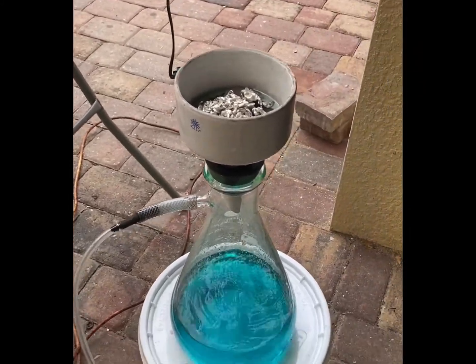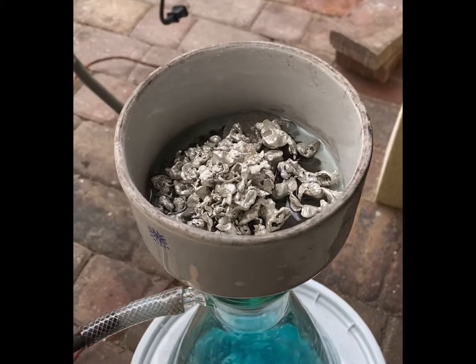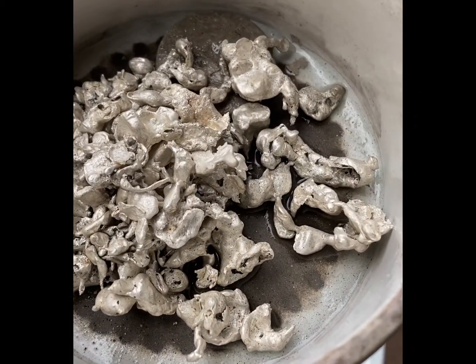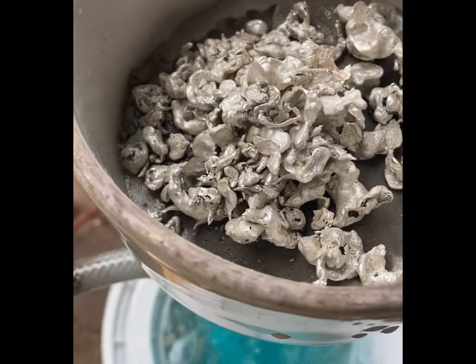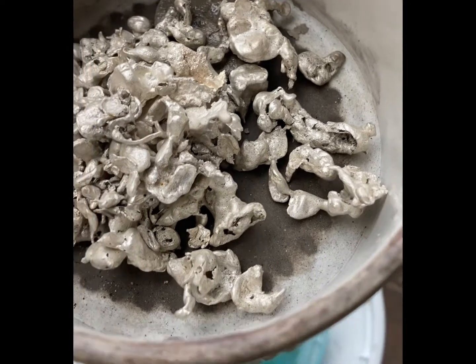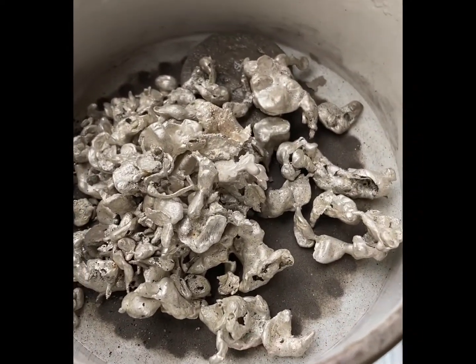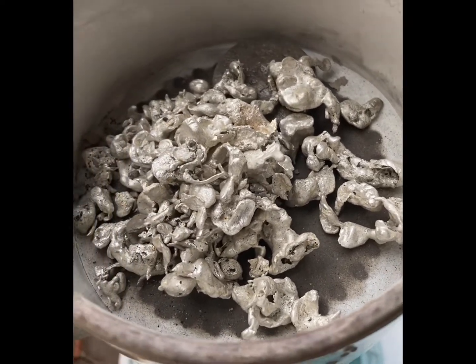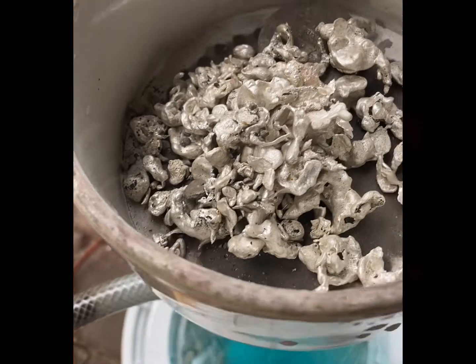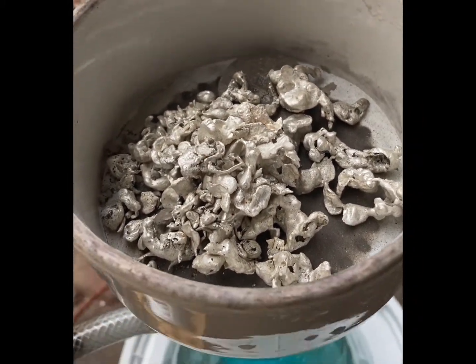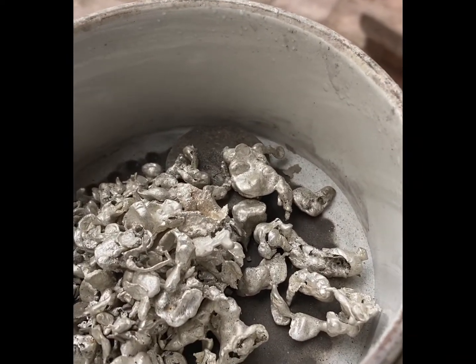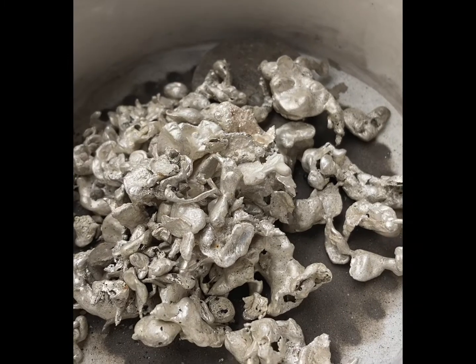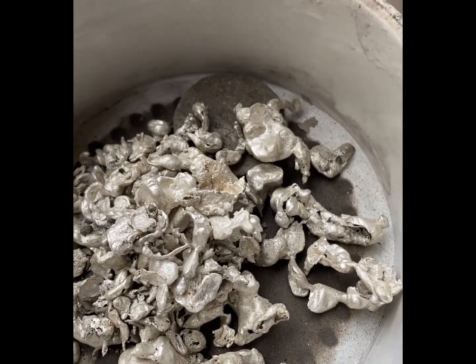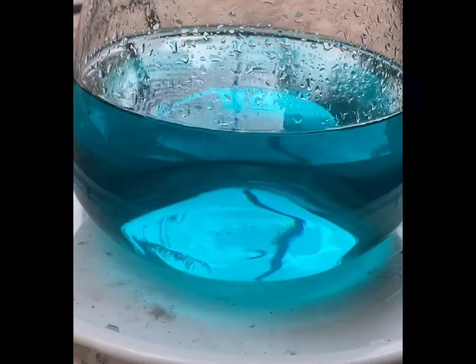All right, so got it all into the Buchner funnel, whatever it's called, and you can see it pulling through the glass fiber filter. And all that gray black that's on the bottom, I'm pretty sure my contamination was two things. It was graphite from the furnace. I think it was an old crucible, and also I may have had some copper in that crucible that contaminated, and that is probably why I'm getting such a blue color. But anyways, all of that black that's caught in the filter is obviously impurities. And now what we end up with is pure silver nitrate. Just sit back and enjoy.